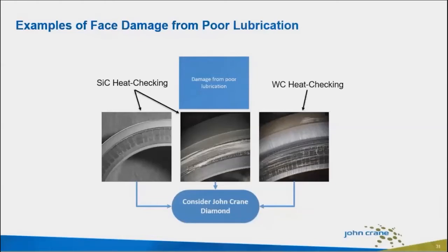Furthermore, sometimes enough heat is generated with traditional seal faces to cause secondary elastomer seals, so O-rings, to overheat and be compromised, which could result in failure for the seal as well. Whenever face damage like this is apparent, this is a great time to consider using John Crane diamond as a solution.